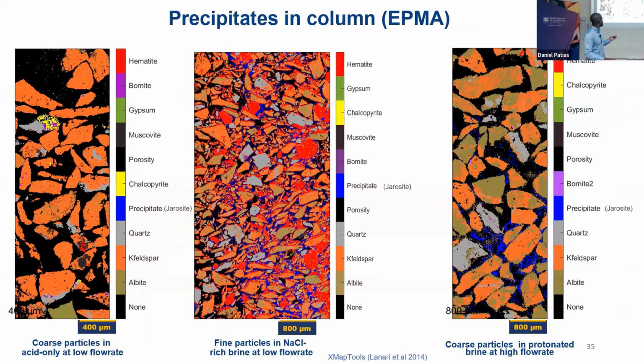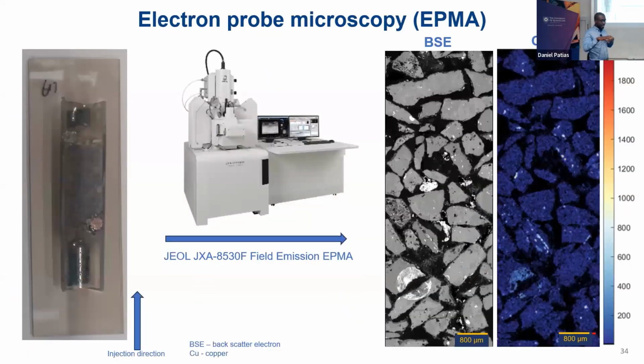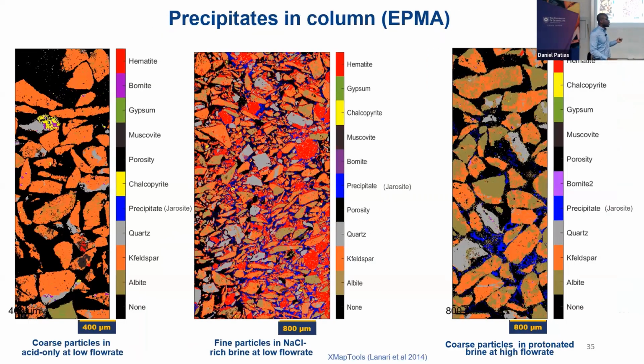So from that same surface, we then pick those points, send it to the EPMA, and that can give us a BSE image and can also give us elemental maps, and we can combine the elemental maps and get a mineralogical map.